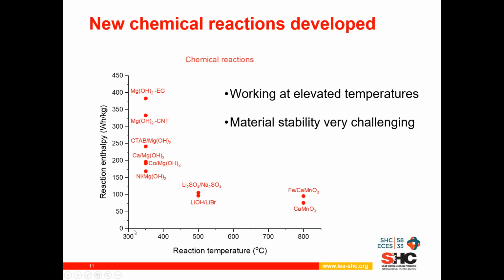Note that here the temperatures are much higher, starting with 300 degrees centigrade up to 800 degrees centigrade. And here is the reaction enthalpy depicted. So typical reaction enthalpies are very distributed for the different materials. Here the champion is the magnesium hydroxide oxide reaction with expanded graphite, which shows that it's between 350 and 400 watt-hours per kilogram of enthalpy change at the temperatures of about 370 degrees centigrade.